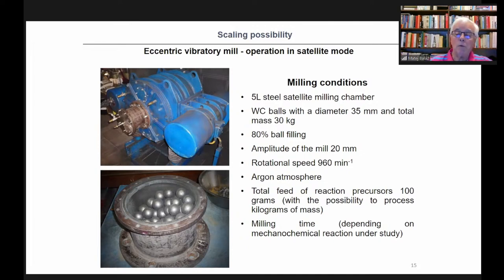In our experiments, we used 100 grams of precursors, which were milled in this satellite. Of course, in principle, it is possible to work with, I think, up to five kilos in one batch mode experiments. And of course, we also play with milling time, which depends on the system under study. But usually we didn't work more than 2 or 3 hours. It was enough to prepare a new material.